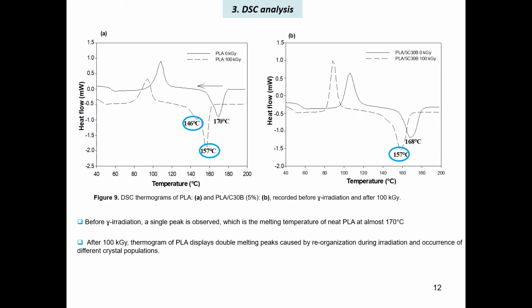Figure 9 shows the DSC thermograms of neat PLA and PLA-based nanocomposite recorded before exposure and after 100 kGy of exposure. In both cases, we observe a decrease in the melting temperature from almost 170 to 157. However, we can see that there is a formation of a double melting peak in the case of neat PLA. And this presence of a double melting peak in neat PLA can be attributed to the reorganization during irradiation of the shorter chains and the occurrence of different crystal populations.